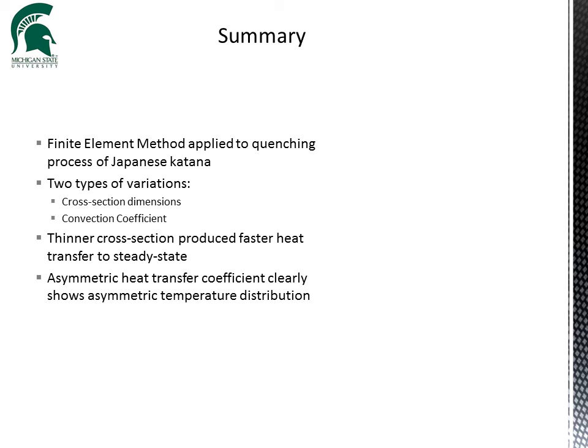And so, in summary, we applied a finite element method to the quenching process of a Japanese katana, varying the cross-section dimensions and convection coefficient, and found that the thinner cross-section produced faster heat transfer to the steady state, while an asymmetric heat transfer coefficient shows asymmetric temperature distribution. Thank you very much.